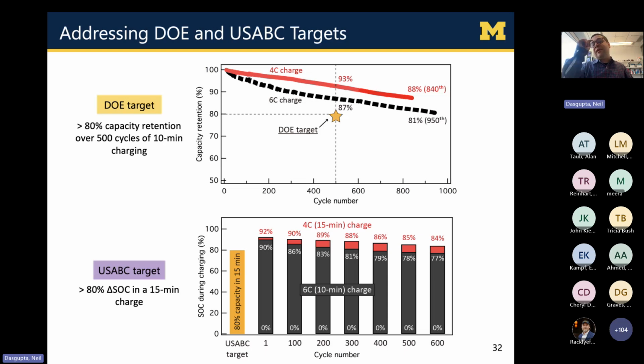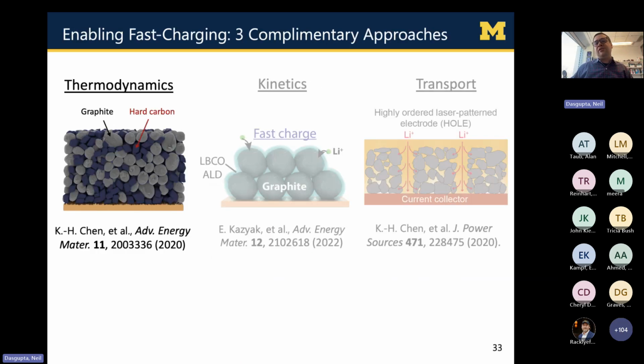And not only can we do that, but we can maintain very high delta SOC swings even after 500, 600 fast charge cycles. So we're able to really achieve that dream of fast charging without sacrificing energy density or the range enabled by recharging our battery.